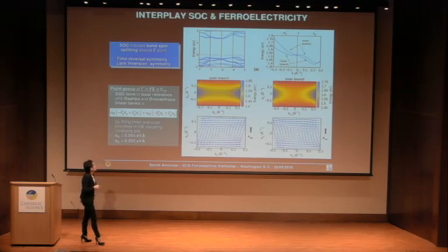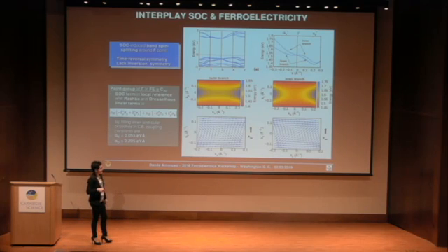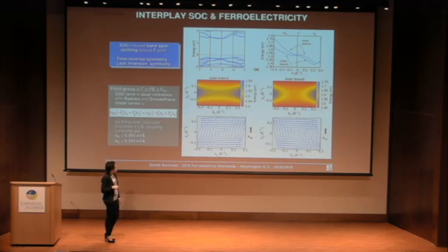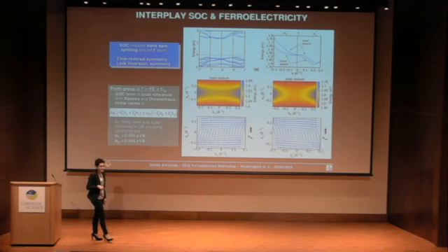We can see a typical inner-outer spin splitting of the band structure, and we can recognize in the behavior of the spin texture the coexistence of both the Dresselhaus and Rashba effects, because we have both the tangential and radial components of the spin orientation.